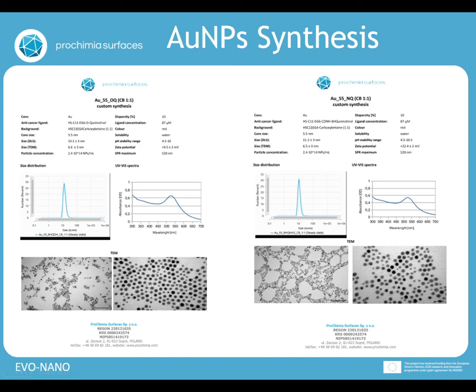So it's larger than the metallic core, but we shouldn't be surprised because DLS is able to detect the ligands attached to the surface. That's why the overall size of the nanoparticles is larger. And over here, TEM images, which are able to show just only the metallic core of these nanoparticles.